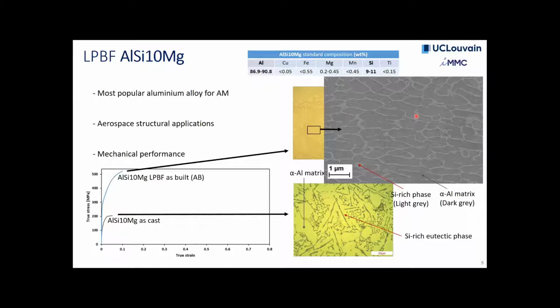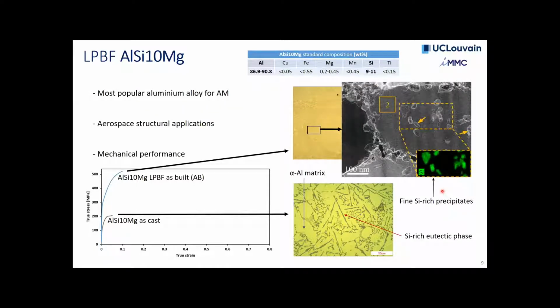Now, if we're zooming in a bit, what we can see here is that these alloys have a very, very fine microstructure indeed. You can see here the scale, and you have silicon-rich phases here that are definitely much smaller, and the alpha aluminum matrix. And if you're looking in the TEM, you can even see between these silicon-rich networks some silicon-rich precipitates in the matrix. So this justifies the difference in strength, and we have shown recently with a very small and simple model the influence this can have on the strength, and indeed these silicon precipitates are quite significant on that side.